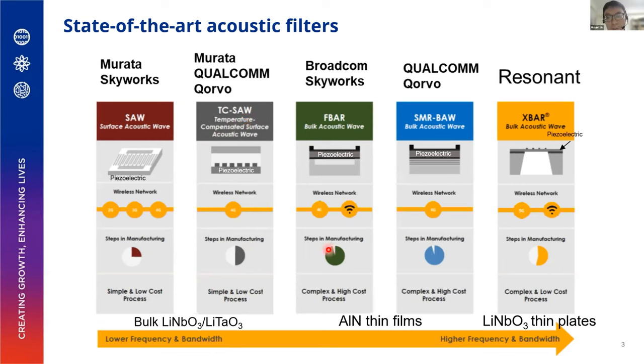Now, as we move on to high frequency and high bandwidth, these two are the major device architectures. They are based on different acoustic wave vibration modes. This is surface acoustic wave, and this is bulk acoustic wave, where the acoustic wave propagates in the vertical direction instead of the in-plane direction. Here, instead of a single crystal, you have thin films sandwiched between top and bottom electrodes. The important thing is that you have to make a cavity below these sandwiched layers so that the resonance is strong and clean and has a wide bandwidth.